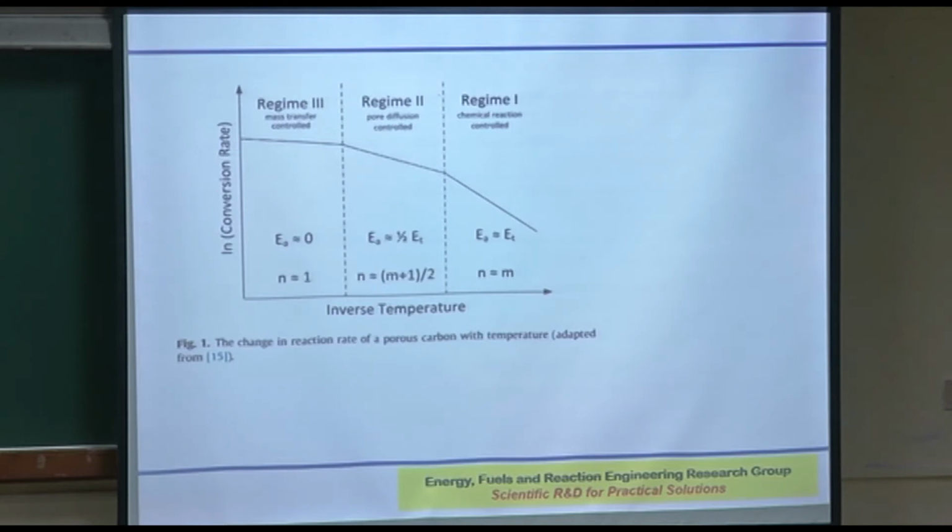So this will also be useful in your case. If you can properly do that in the TGA, you should be able to find out, in presence of your oxygen carrier, what region of TGA experiments will give you the true activation energy. Because as I said, it is very important to get that information, even though in reality this is what will be dominating. Okay.